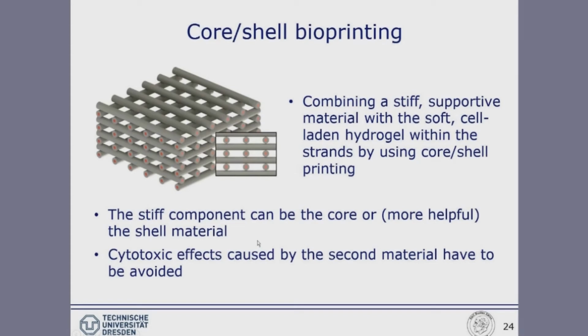The stiffer component can be the core, or, and maybe this is the more effective way to do it, it could be the shell material, and therefore helping, protecting, supporting your soft hydrogel, which then, of course, has to be the core material. You have to keep in mind, due to the very close interaction of the two materials, that of course there may not be any cytotoxic effects from the second material, which therefore has to be selected quite thoroughly.